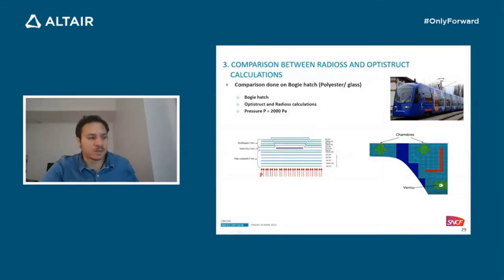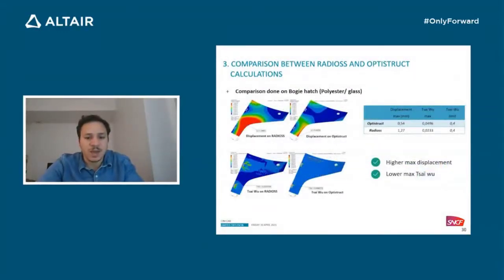It is put on the external surface, as we can see here, and we use two types of material cards for the ply: mat and taffeta. The composite is made of 2 point inserts and 1 lock point below. The result of the comparison is shown in this slide. As we can see, concerning the displacement, it is different because of the decrease of mechanical characteristics with nonlinear behavior of the composite compared to the linear calculation with OptiStruct. It introduces more flexibility. However, concerning the Tsai Wu index, the OptiStruct calculation is above the Radioss calculation. We can conclude that using OptiStruct is okay and faster than Radioss.